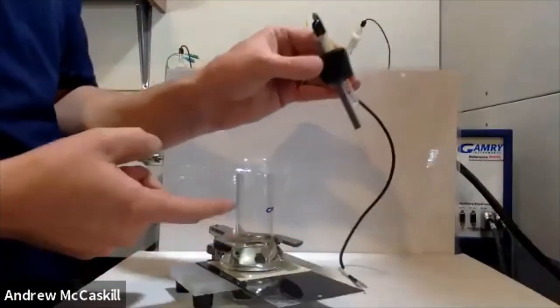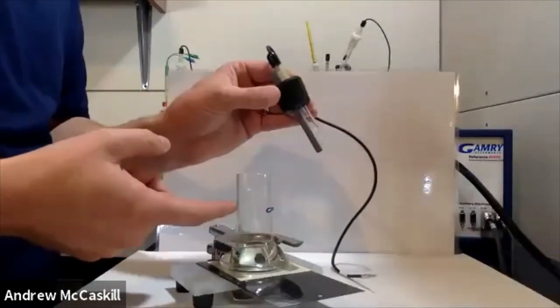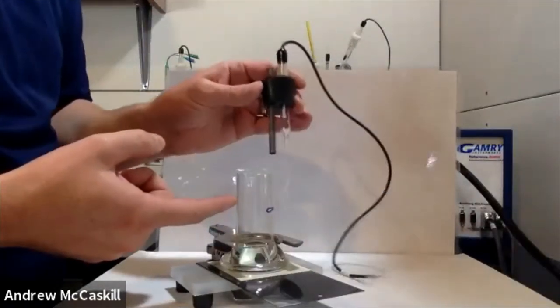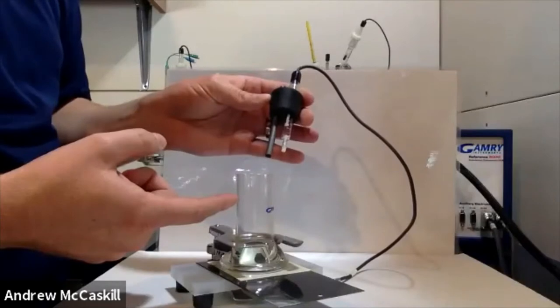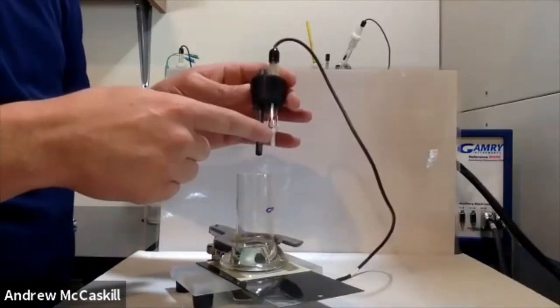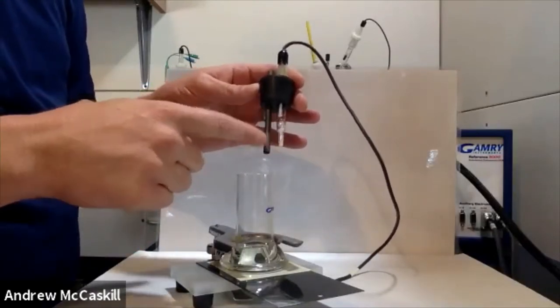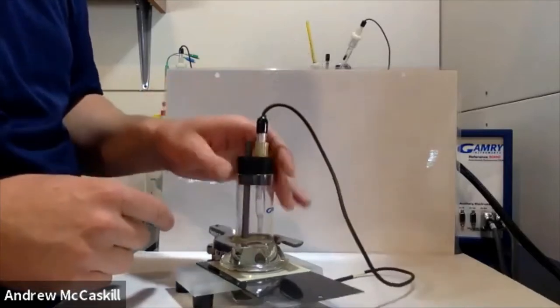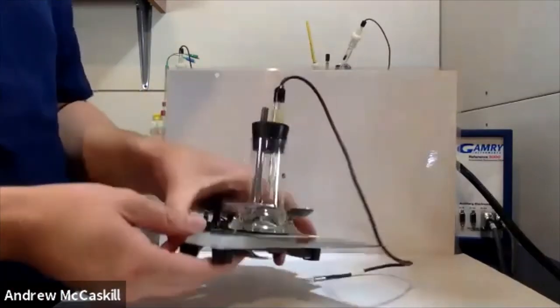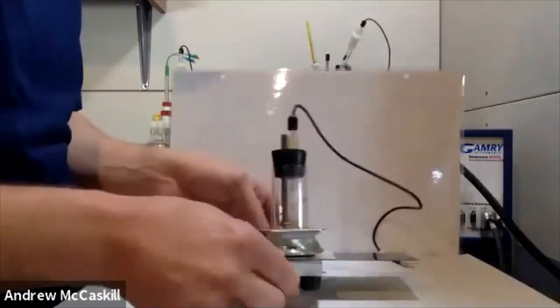So we can fill up the volume here to anywhere from about 20 to maybe 50 milliliters of solution. I just want to make sure you have enough in there that you contact the tip of the reference electrode and immerse also the counter electrode. It'll fit in like so. And there's your simple three electrode cell for a flat specimen, coated specimen, something like that.